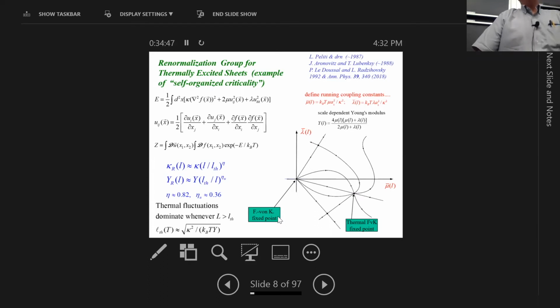Other questions? Yeah. There's something that smells like a Goldstone mode, with high order corrections for your order parameter. Yep. And you know that nonlinear theory, because there are two fields involved, the in-plane phonons and the out-of-plane flexural phonons, it evades what in other settings would be the Coleman theorem and so forth. So there are boson modes, there's no doubt about it, but because the bend rigidity gets renormalized so strongly as a function of length, those logarithmic divergences that you might be familiar with go away. Okay.